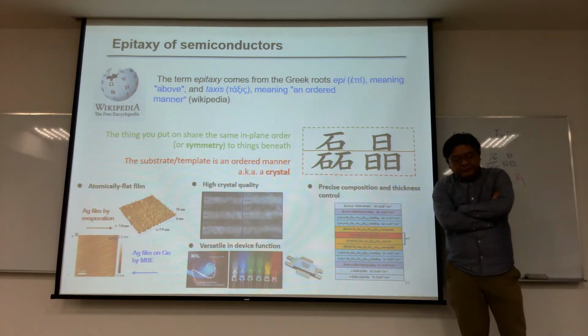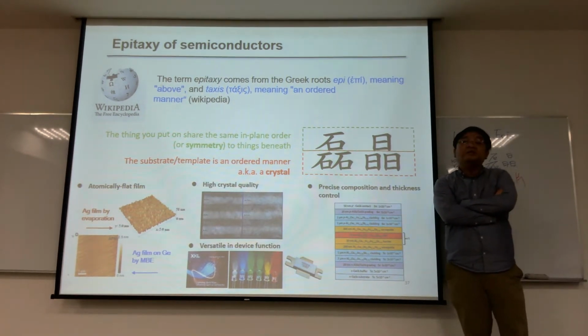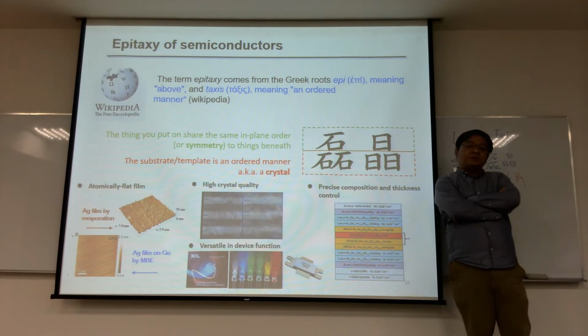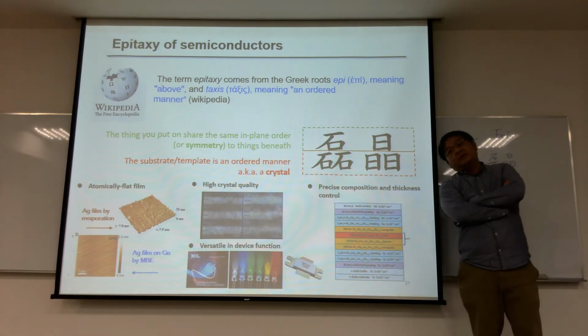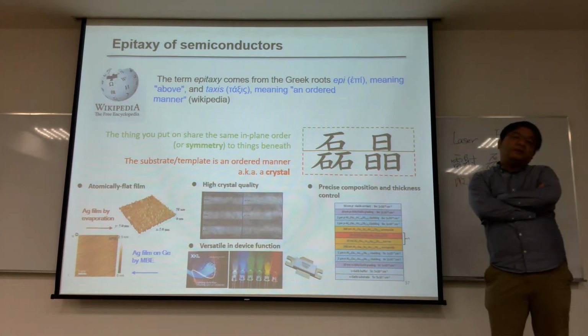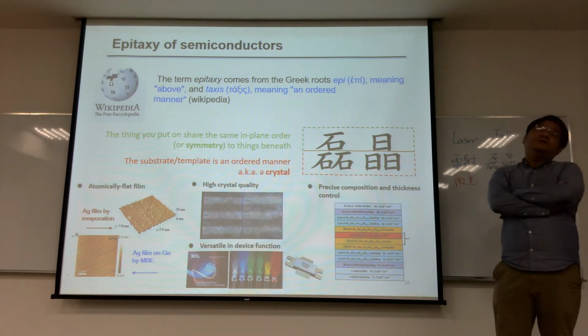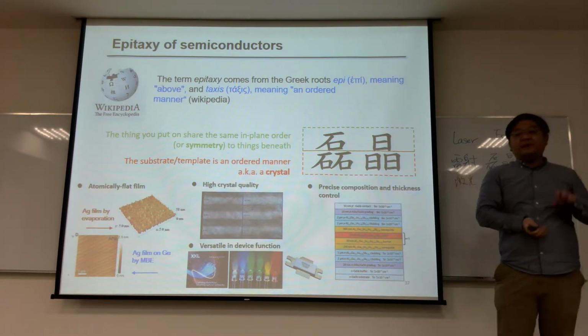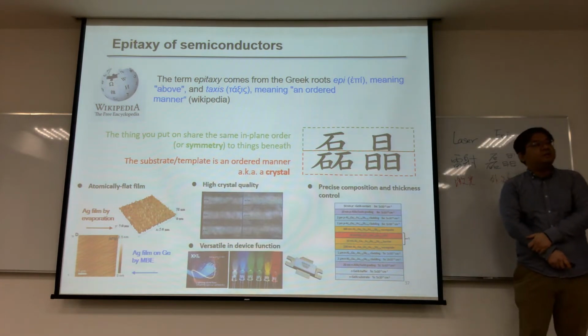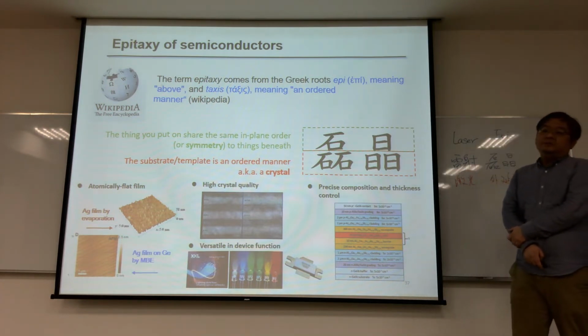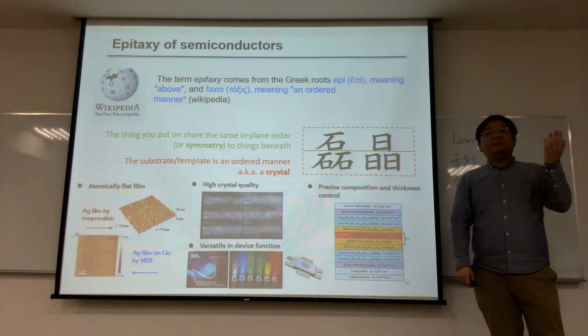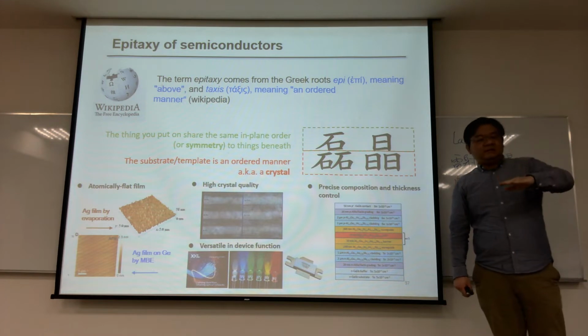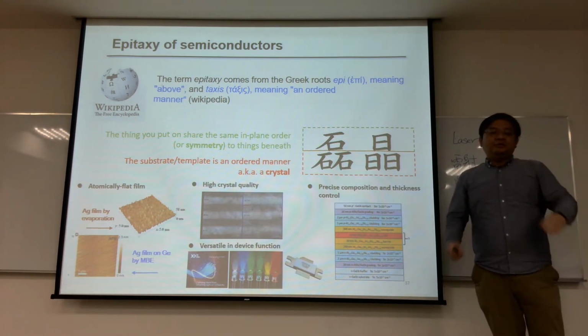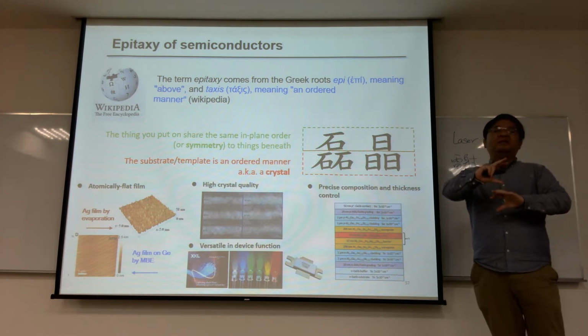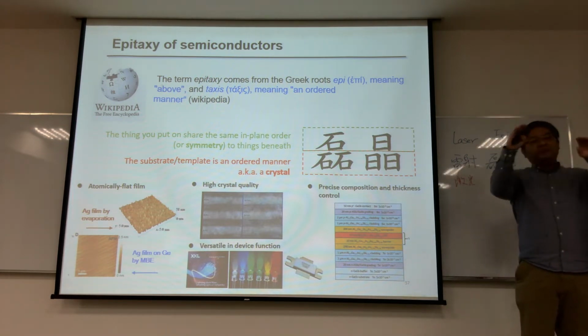For example, if we just mentioned the PIN structure, the DH structure, you have 3 layers: P-type material, I-type active region, and the N-type material. However, in the common VCSEL, the vertical cavity laser in your cell phone, it usually has around 100 layers. Because you want to grow something called the DBR, that is a mirror constructed layer by layer by layer. And you usually need 40 layers to get a very high reflectivity. So bottom 40 layers, top 40 layers, and probably more structure in between.